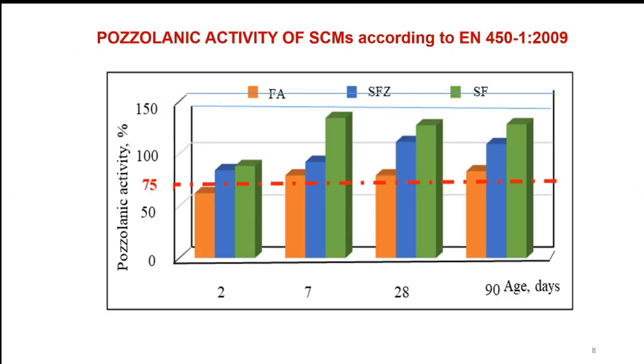According to the European standard, the strength activity index after 28 days should be more than 75%, and after 90 days, more than 85%. As can be seen from the slide, superfine zeolite and microsilica reach the corresponding indicator already after 2 days of hardening. The strength activity index of fly ash meets the requirements of the European standard, but is significantly lower compared to superfine zeolite and microsilica.